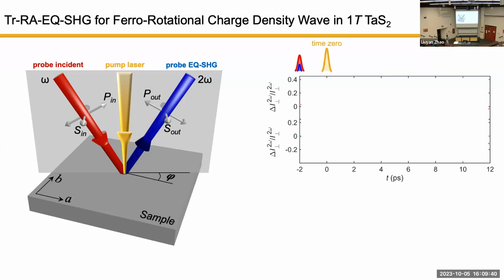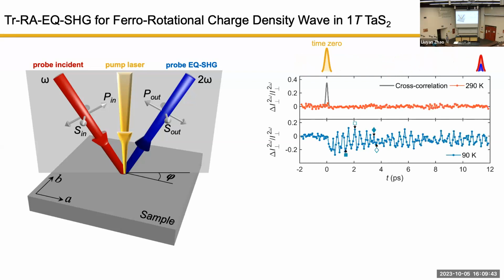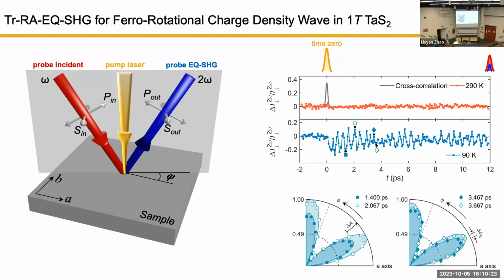Once we do that, you will see these beautiful oscillations pop up in the time-resolved measurement. The horizontal axis is in time scale of picoseconds. But different from time-resolved linear optics, where a change of intensity is just a change of intensity, in nonlinear optics, since we have this anisotropic flower pattern, a change of intensity at one angle is actually convoluted by two things. One is the flower pattern becoming big and small. The other is the flower pattern shaking left and right. Even if the size does not change, once you shake at a single angle, you will see a change in intensity. So that's the two cases.